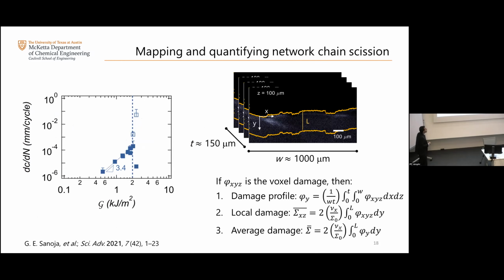Now, let's get to the damage part. How much were they damaged and how do we quantify it? Again, what we have is a stack of images that we collect under the confocal microscope. We image about 1 millimeter, or 1,000 microns, in this direction, and then about 150 microns depth in our elastomer, okay? Then when we collect this stack of images, we can integrate the intensity of the voxels in 1, 2, or 3 dimensions. That enables you to obtain a damage profile. If you integrate in 2 dimensions, you can obtain a local map of damage. If you integrate in 1 dimension, you obtain a profile. And if you integrate in 3 dimensions, what you get is an average of all the damage that you have. I will show you examples of the profiles, of the maps, and of the averages in a second. But if you want to see details of the quantification, you can find them in the paper.